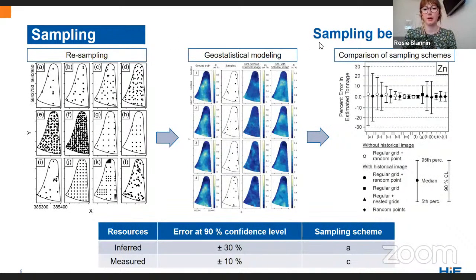And if we want to think about this in terms of errors and uncertainties on the results, then we decided to look at the tonnages. So we estimated the tonnage corresponding to the original simulations, and then we estimated the tonnage after the resampling and modeling again, and compared these two results. And the figure on the far right shows that as you increase the number of samples, so from scheme A to F, the error in the estimated tonnage significantly decreases.